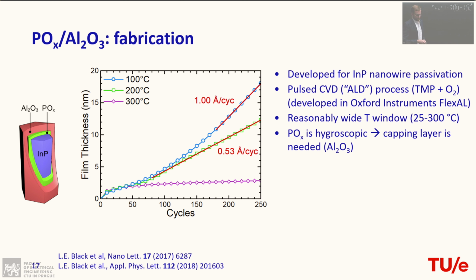So this layer stack sounds quite exotic. It's not really a classical material for PV purposes, and people have not looked at it for a very long time. It was originally developed by a colleague of mine from Eindhoven, and he looked at this material for a different kind of technology, for nanowires. Nanowires are a 3D surface, so you need some technique that can conformally coat this difficult surface morphology, meaning the route was chosen for ALD, and they developed a recipe. So it was possible to grow this at different temperatures, and it was growing quite all right.